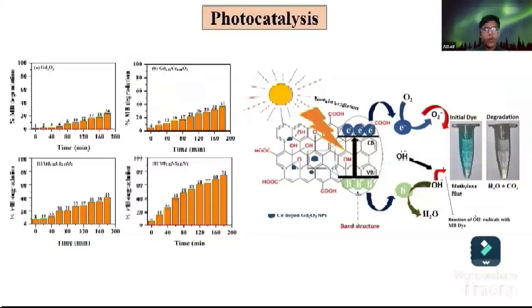When sunlight falls on our cerium-doped gadolinium oxide nanoparticles, the material absorbs this light energy. Because of this, electrons get excited and move from the valence band to the conduction band, leaving behind positive holes. Cerium doping plays an important role here as it reduces the band gap. It helps in better separation of these electrons and holes and reduces their recombination, which also increases the efficiency.